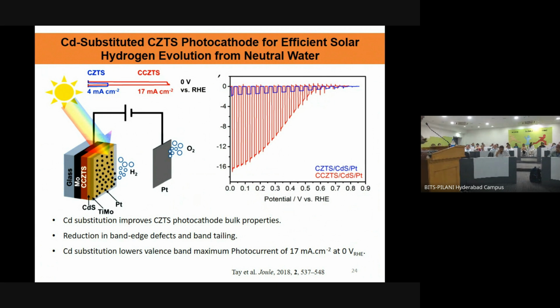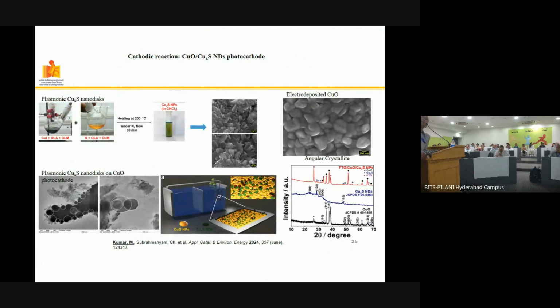So then what we took in this case, in our study, the student has done in a way like the copper oxide, which is a known p-type material. So the Cu2, I cannot say Cu2S because this is a non-stoichiometric thing, but at least like sulfide. Okay, so the ones we try to reduce with an organic linker, for example oleic acid, and this kind of combinations we have used.